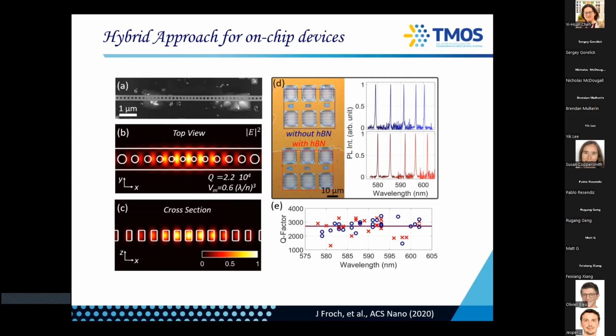And so there are a few take-home messages here. The most important thing is that the HBN doesn't actually degrade your quality factor. Typically in the photonic crystal realm, if you put something on top or if you don't make it perfectly designed, your quality factor will degrade. In our case, it's actually the same. So the red lines here, these are not emitters. This is just a resonance of the cavity that we control around 600 nanometers. And you can see that with and without HBN, the quality factor is nearly identical. So it is around 3000 or so.